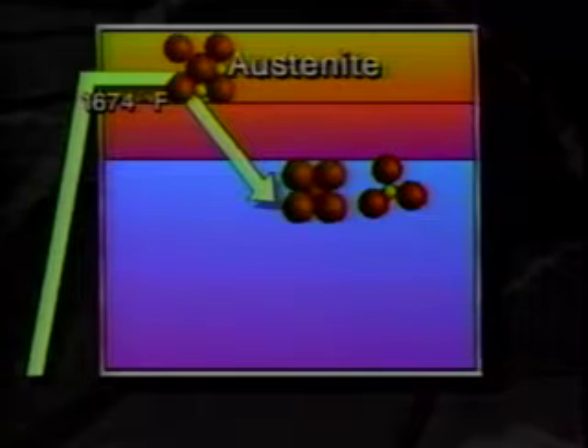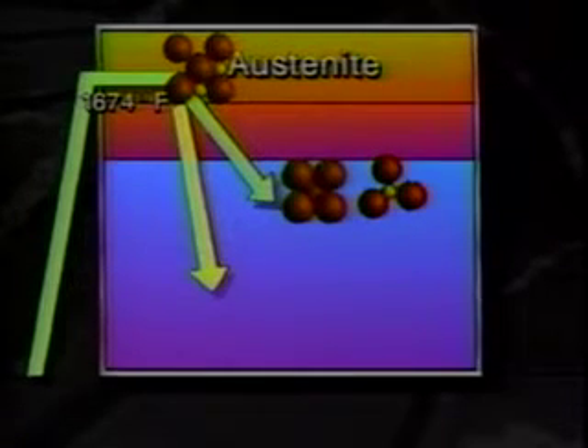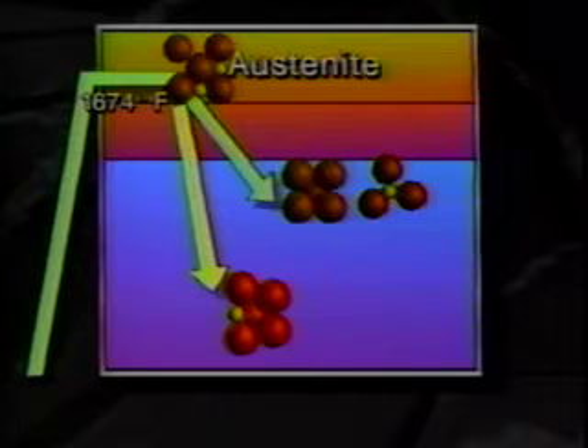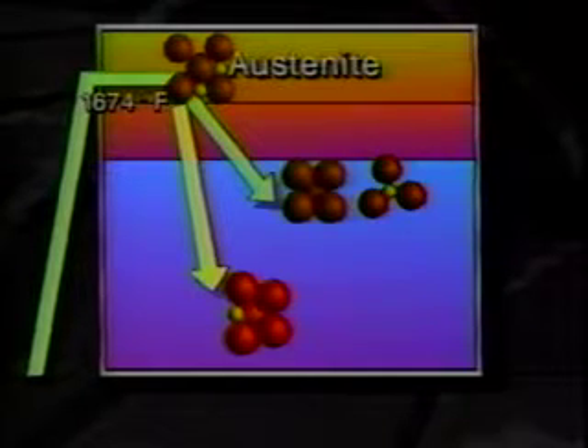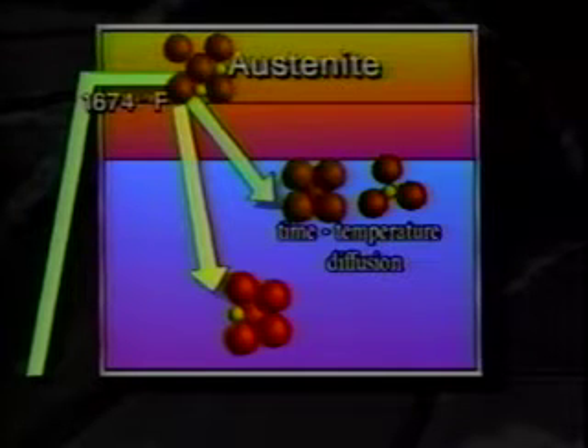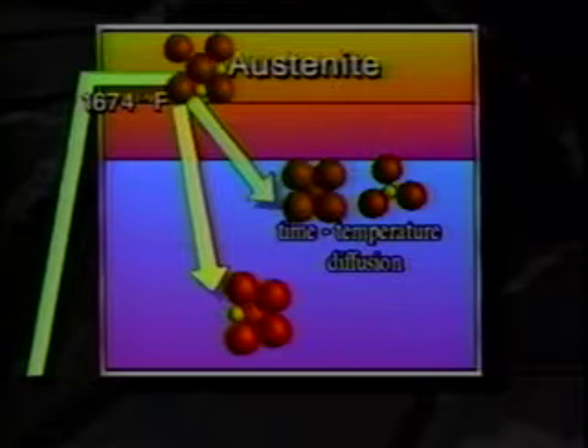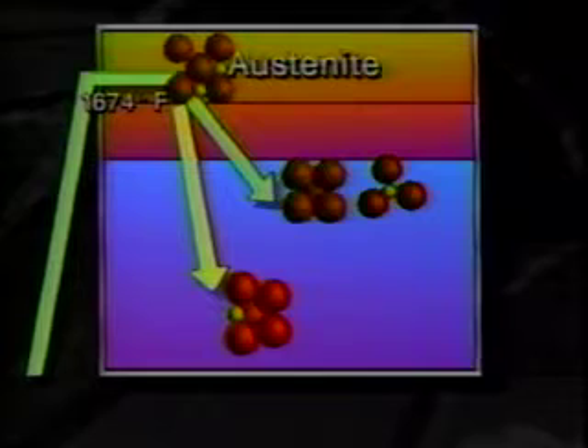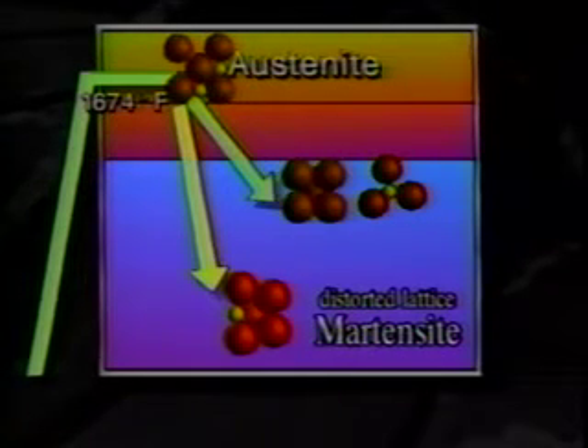If the austenite is quenched rapidly, the carbon atoms remain trapped within the crystal lattice because the segregation of carbon atoms in the form of iron carbide requires a time and temperature-dependent process called diffusion. Quenching, that is, rapid cooling, forces the carbon atoms to remain in solid solution in the iron, even when the temperature is well below the lowest temperature at which austenite is stable. This causes a distortion of the austenite. This distorted lattice is martensite.